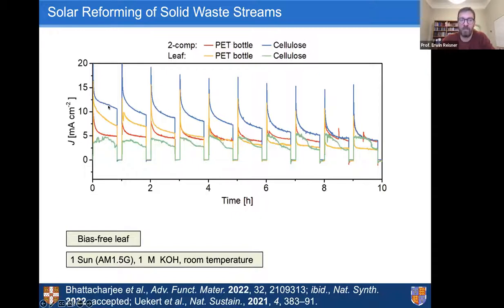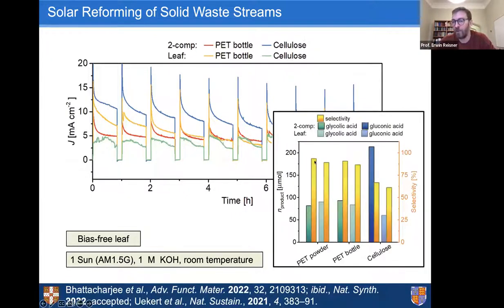So actually, in terms of product rate per area of irradiation, there's a significant advantage using waste substrates and replacing water oxidation. And also, we already have reasonable control over the product selectivity on the oxidation. From the products I've shown before, glycolic acid or gluconic acid, we reach selectivities already from 65 to 95%. So there's still improvement required, but as a starting point, I'm quite happy with that.